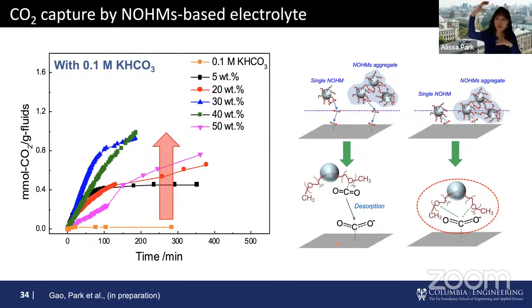But what if NOHMs delivers that CO2 to the surface of the catalyst and then kind of hovers around during the CO2 conversion? Then maybe this interaction with all the tethered polymer on NOHMs will bend CO2 just right so that its conversion is taking very different pathways. This could change the Faraday efficiency.